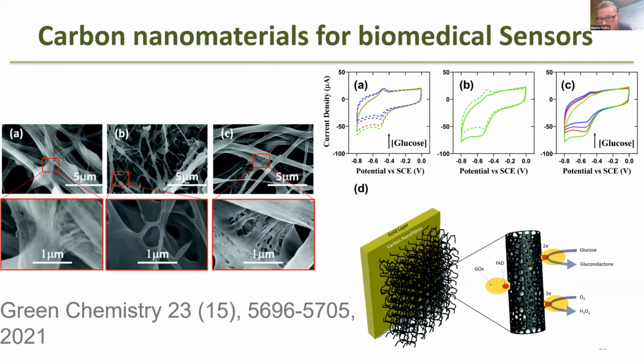We use the same materials, these porous nanofibers, for diabetes treatment. The idea here was that we produced these nanofibers, we put them on a gold layer, and we were able to detect glucose. So it was a quick detection of glucose. We use them as a diabetes sensor for glucose.